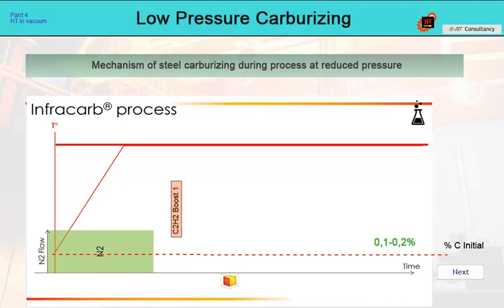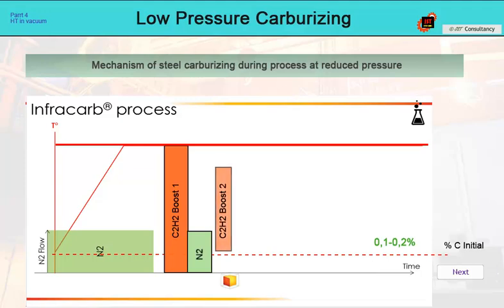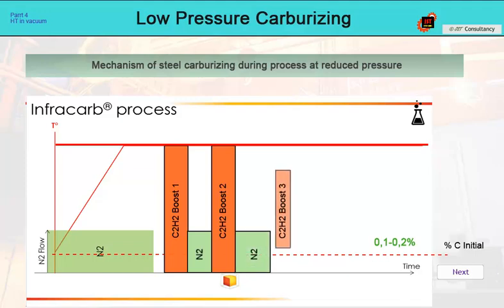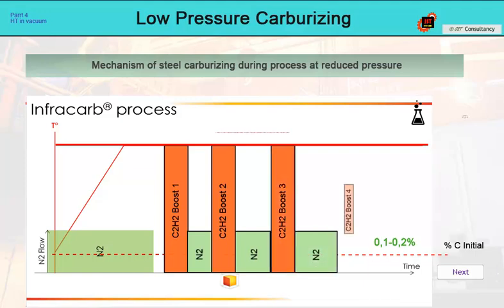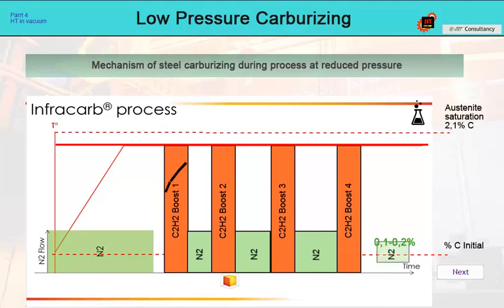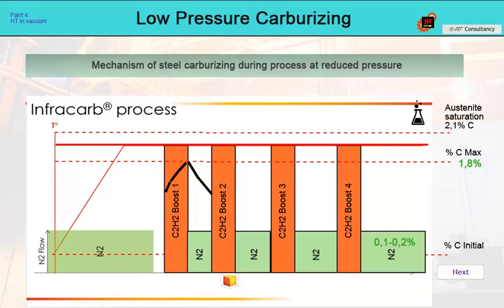The carburizing process begins with the first saturation period and is followed by the first diffusion period. The next periods depend on the required carburizing depth of the CHD. In our case, these are 4 periods. The saturation period provides enough carbon to saturate the austenite at the ACM line. The maximum can be 2.1%, but in the case of carburizing at 960 Celsius, it will be only 1.8% of carbon.